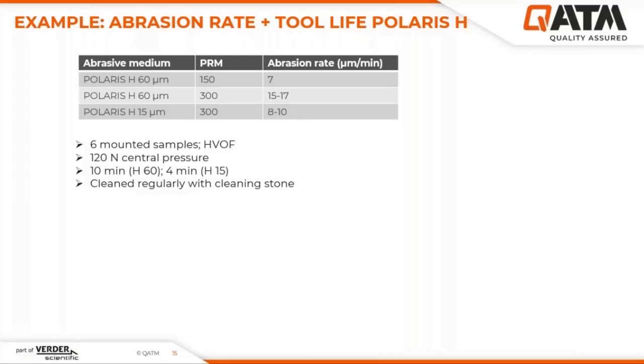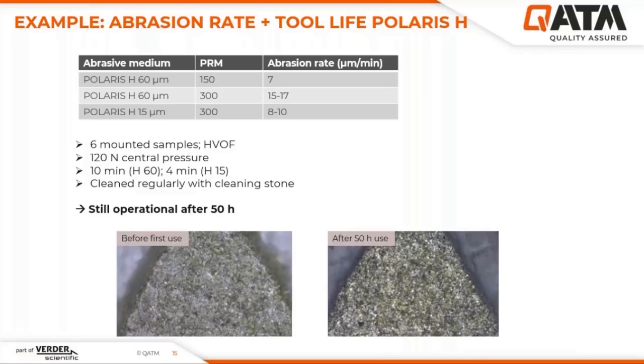According to the protocol, the 60 micron disc had a total operating time of 50 hours and was still fully operational afterwards. During the study, it was regularly cleaned with the cleaning stone. Here you see a picture of a grinding segment before and after the 50 hours operating time. You can see how the thickness of the segment has decreased significantly.